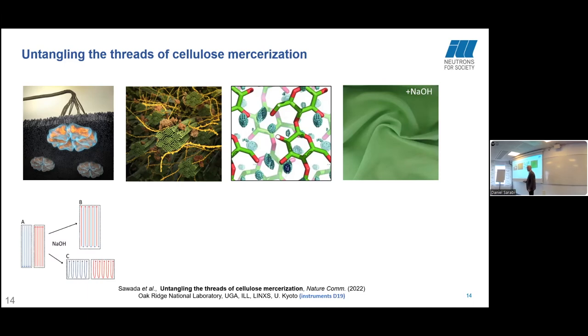And actually, two people have come up with different proposed mechanisms. If you've got two nanocrystals sitting next to each other, and one's pointing down and one's pointing up, perhaps when you treat with sodium hydroxide, the two neighboring nanocrystals can swap chains or merge together so that you get parallel and antiparallel chains. That mechanism was proposed by John Blackwell and his colleague Kolpak back in the 1970s and 80s. Another possibility is that rather than the chains from different nanocrystals mixing, within each nanocrystal the chains can fold back on each other. So you get a zigzag pattern of chains. That mechanism was proposed by someone from Grenoble, who I collaborate with, called Henri Chanzy. So these are two possible explanations for what happens here.